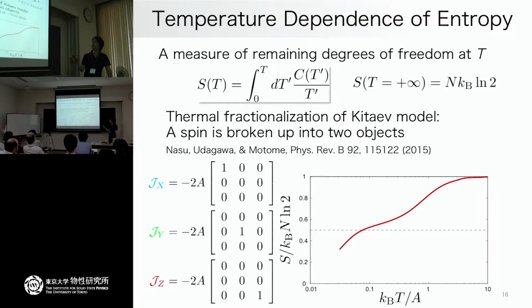Then these people, Professor Nasu, Professor Udagawa and Professor Motome, found a way to calculate the finite temperature property of the Kitaev model by using Monte Carlo. Then they can calculate the thermal excitation of the Kitaev model. And they found that the spin degrees of freedom break up into two objects even at finite temperature, and this is observable in the temperature dependence of the entropy.